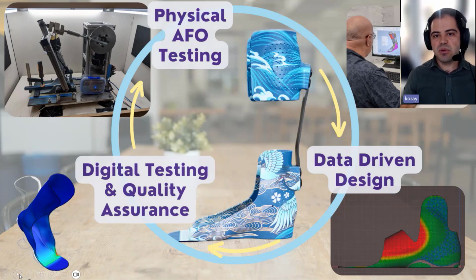So I want to share a few learnings that we've had, and I'll be lying if I said 3D print works for every client and device, of course. So if you need a super stiff, thin device, 3D print is not going to cut it. We tried going down the pathway of incorporating triple action joints and Euro springs into our devices, but to get the same stiffness of a comparable carbon fiber laminated device, I'm not even talking about pre-preg, not even trying to go there, we ended up with a really thick, really bulky, heavy device, and it just didn't have enough torsion rigidity, even when we got up to really high thicknesses. So where do we go from there?